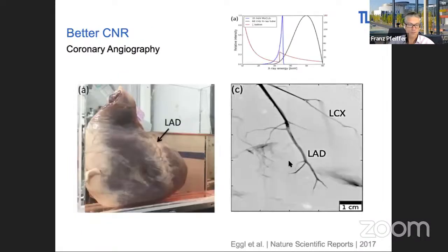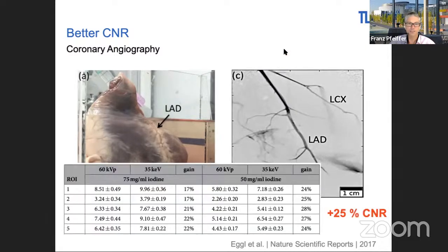At synchrotron sources, coronary angiography has been looked at for a while because you can tune your monochromatic spectrum right after an attenuation edge of a contrast agent. In this case, we had a little mock-up experiment with a pig heart, injecting some iodine contrast agent in the coronaries. You can nicely visualize them by tuning into the sweet spot after the attenuation edge. And you can show that you get at least a 25% increase in CNR if you use a perfect spectral matching to the source.